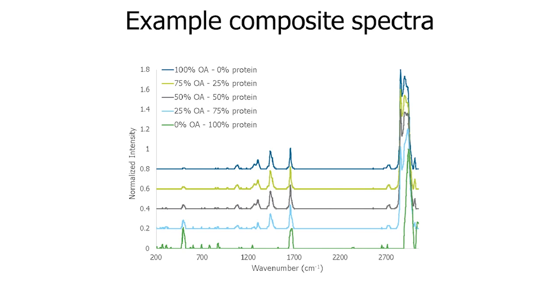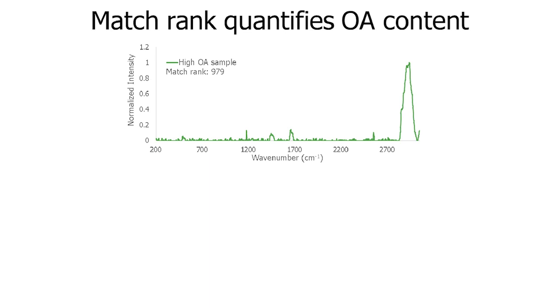So between pure oleic acid and pure protein, we're seeing composites for 75% oleic acid, 50% oleic acid, and 25% oleic acid. But remember, this is just a subset of the database. This was actually done at 1% intervals. What you can see with this is these composites start looking pretty similar. Since we're looking at these 1% intervals in the ratio between oleic acid and protein, we expect that the spectra are going to look quite similar to each other within a narrow range. Because of this, we need to quantify the best match.